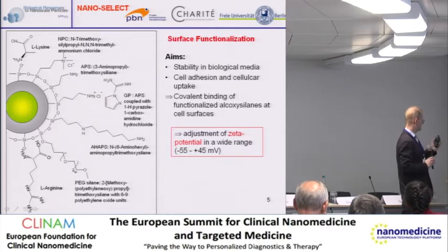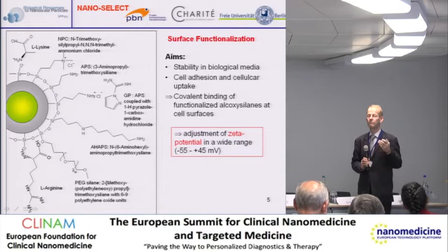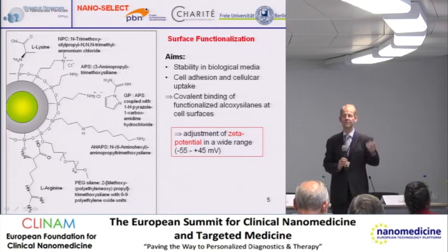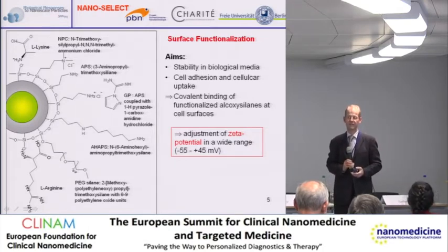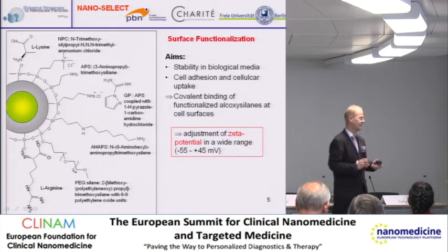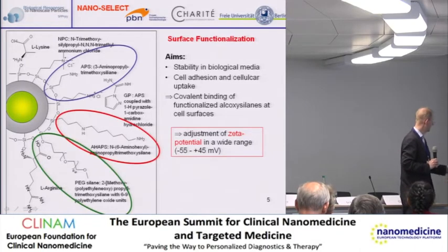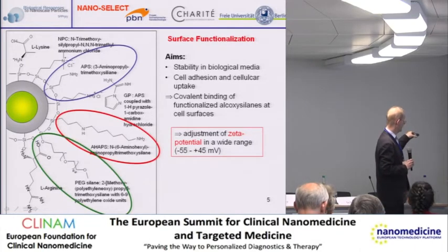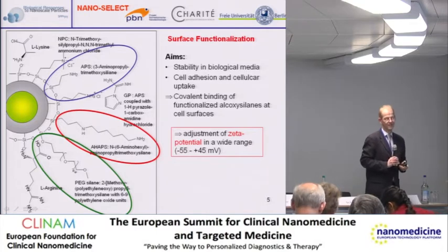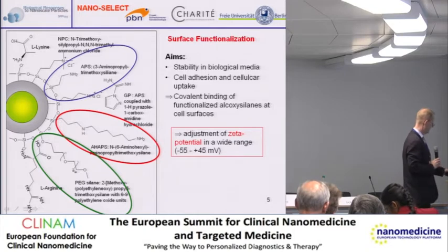And I will just go here through a few functionalizations of positive zeta potential, because we learned that this is advantageous for cellular uptake because of the negatively charged patches on the cell membrane. And I'll just show here the APS ligand, the AHAPS ligand, and the PEG-silane ligand. These are ligand systems that we studied regarding their uptake behavior more intensively.